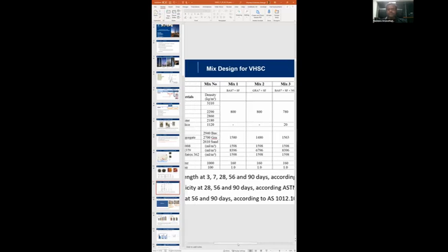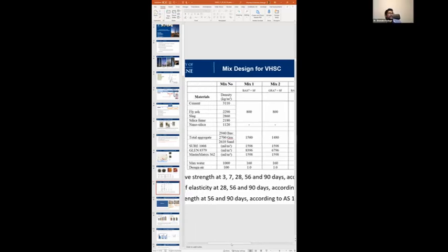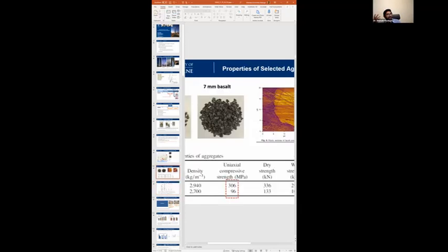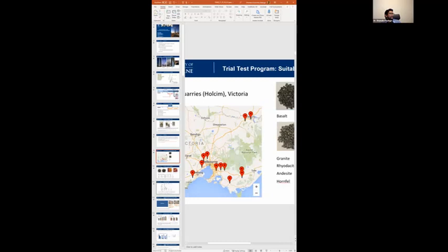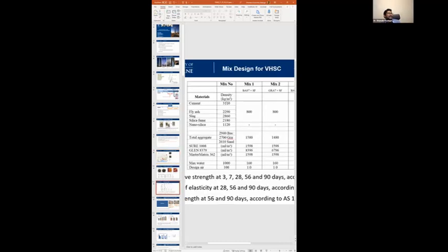I can see. Actually, even before the nano indentation, Professor, we revealed the secret of what is happening in high strength concrete by looking at the density. So this is the specific true density. This is not the bulk density. Can you look at these numbers? The cement is the densest, 3.110, because we know it is mostly silicon dioxide with calcium oxide.